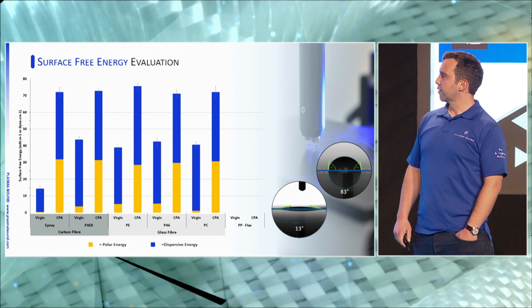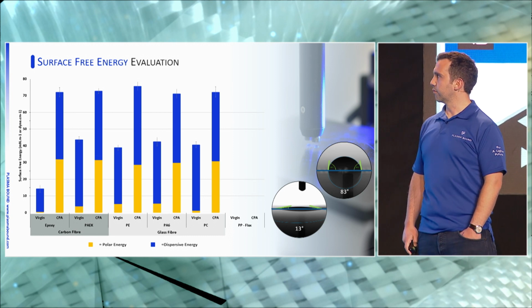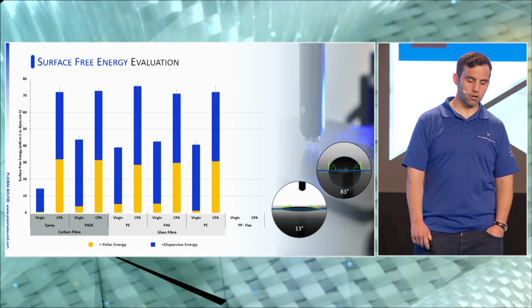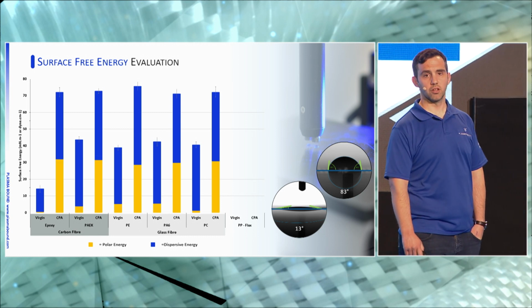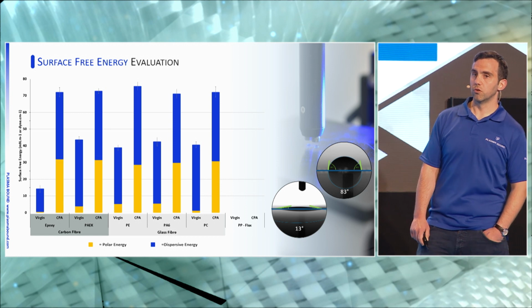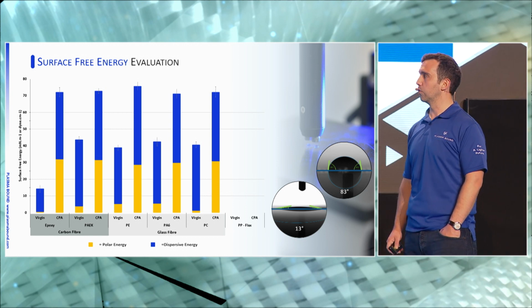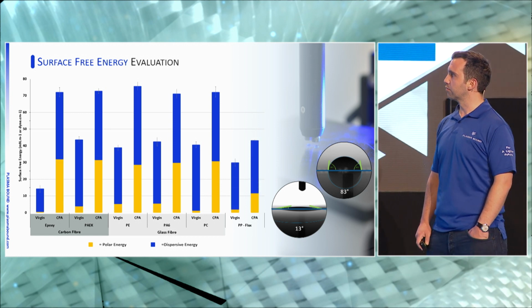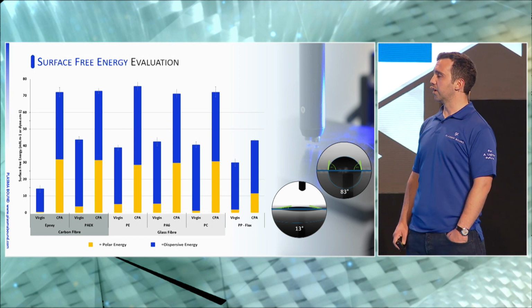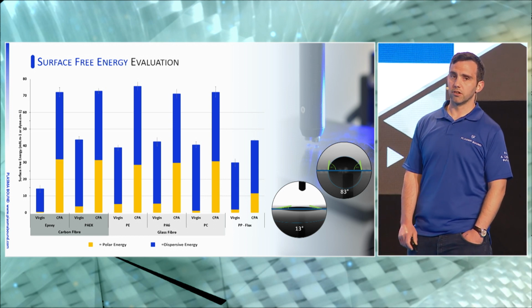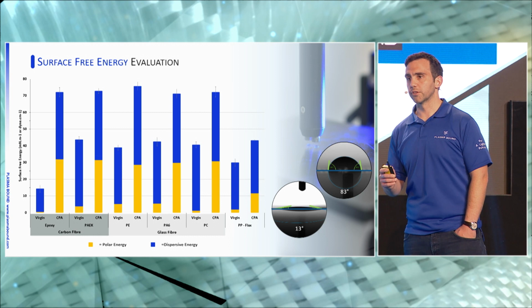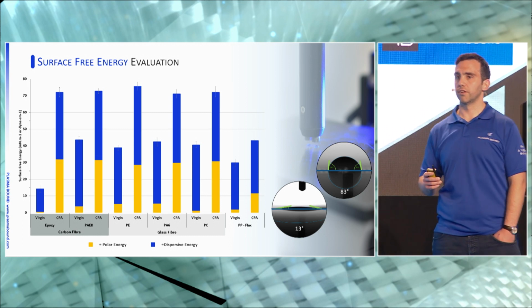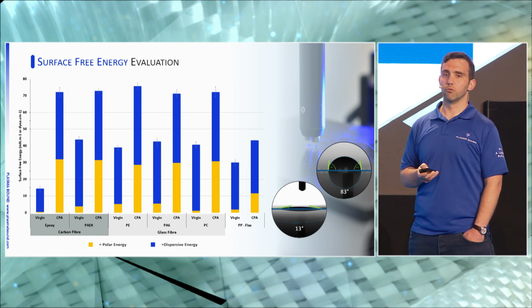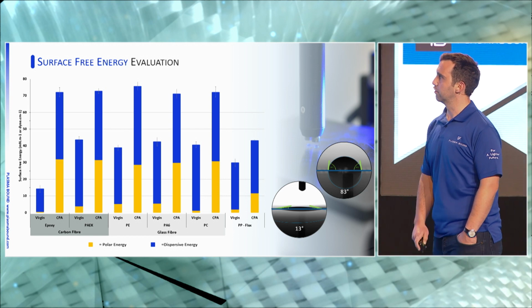When we go to the commodity level materials, polyester, polyamides, and polycarbonates with glass fibers filled, again, you see across the board an increase in both the polar and dispersive response because of the skimming method that we use. So we don't just increase polar, we increase both. And then when you look at the future-focused materials like polypropylene with flax, we do increase the surface energy. However, we have to respect the fact that it's a biomaterial, the flax, so it doesn't have as much energy resilience as other materials.